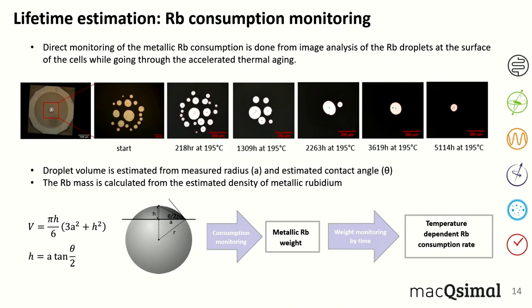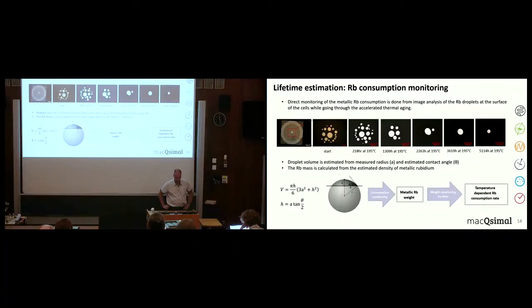A very important part of the project was dedicated to lifetime estimation. I already mentioned rubidium is extremely reactive. And indeed, if you put a cell with decomposed rubidium azide, so you have the rubidium directly at the start, and you expose this to a temperature of 195 degrees, you see over time the small droplets disappear and form bigger droplets, and the bigger droplets disappear also. So we monitor the metallic rubidium consumption based on image analysis.